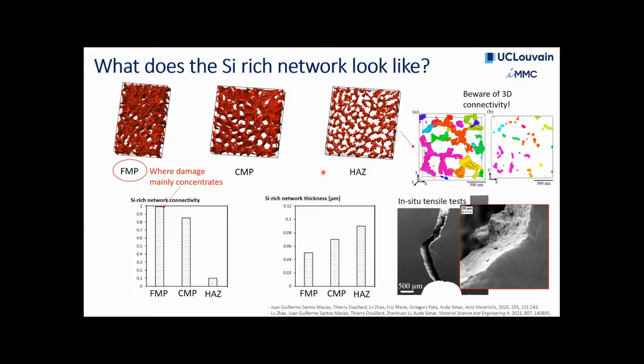And so if you have a high connectivity of network, basically the network breaks. Here in the heat affected zone, I just wanted to mention that we should be careful when we're talking about connectivity in the heat affected zone. When you look into these, it really doesn't look connected.